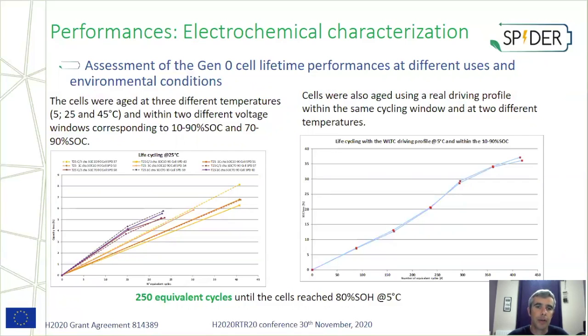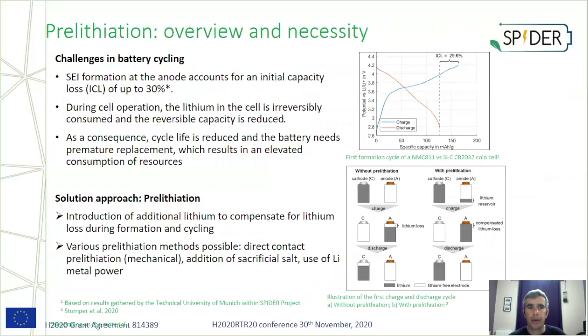We haven't yet finished the analysis of the tests, but we already saw that we can get 250 equivalent cycles until the cells reach 80% of state of health at 5 degrees, which is quite interesting. To improve the cycle life, we developed the prelithiation process. The graph at the top right shows the first formation cycle of a cell. You can see there is an initial capacity loss due to the solid electrolyte interface formation, the famous SEI. And there is also lithium consumption upon cycling.